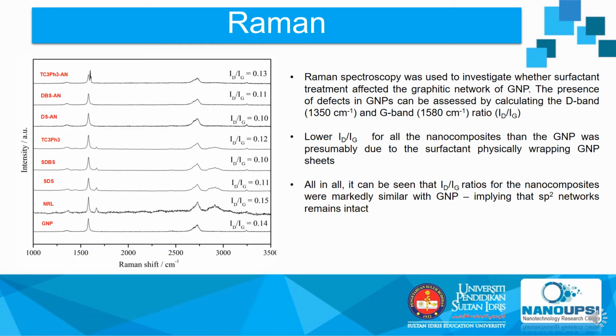In order to study the defects of the composite by the introduction of surfactant, we did Raman spectroscopy, and this is indicated by calculating the ratio of the intensity of the defect band at 1350 and the graphitic band at 1582, which we call the ID/IG ratio. And as you see, all the composites provide a similar ID/IG ratio, indicating that the sp2 network of the GNP in the composite remains intact.